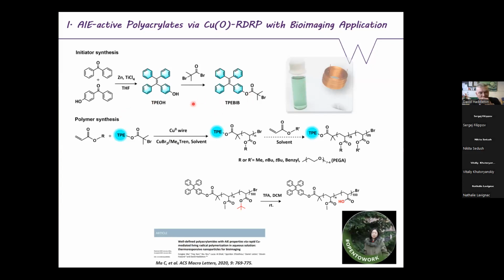In all of this chemistry, as long as I've got an alcohol, I can esterify it with this commercially available acid bromide, which we do. Our undergraduates make these. In fact, our undergraduates do reactions using copper(0) disproportionation to make polyNIPAM. We have no Schlenk lines, and we don't even bother to measure the oxygen level. We did it a couple of weeks ago, and they all make polyNIPAM with dispersity less than 1.1.